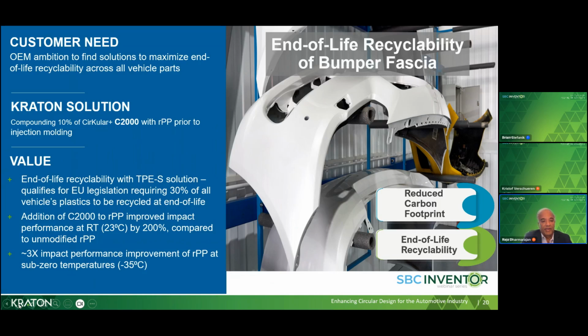So what we notice here is we measured both notched Izod at room temperature and low temperature. With the addition of about 10% of the C2000, we are able to increase the notched Izod by almost 200% at room temperature. But more importantly, and what is more impressive, is at minus 35 degrees C, that is the cold temperature impact, we are able to enhance that by a factor of 3. So the CirKular+ modifiers are very effective in enhancing the performance of RPP, as you can see from this slide.